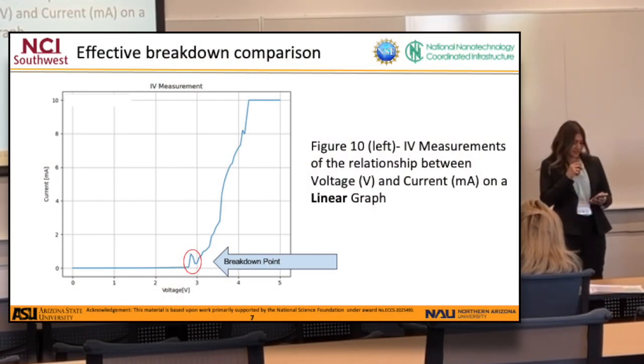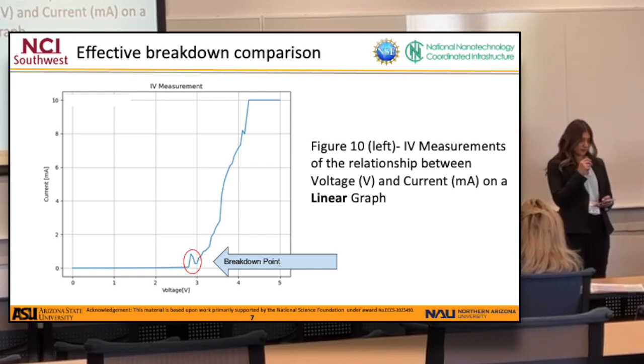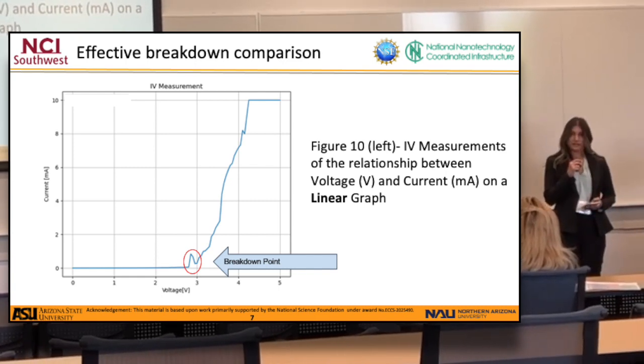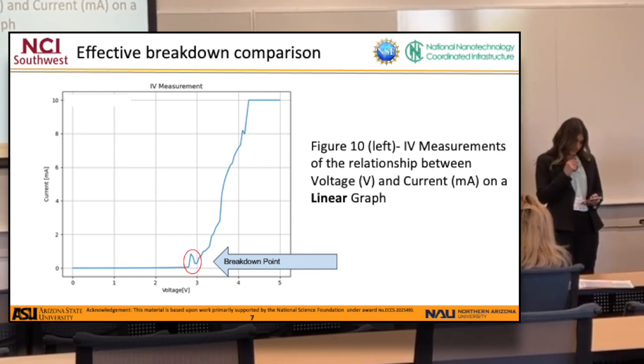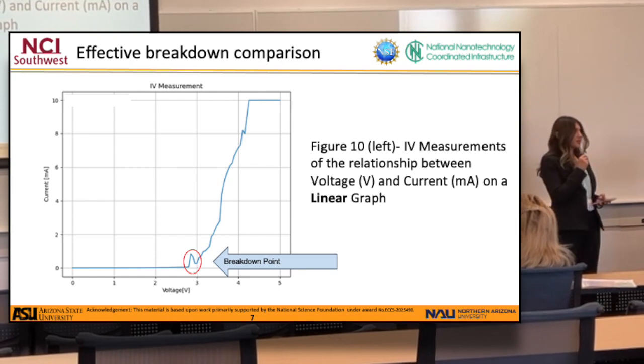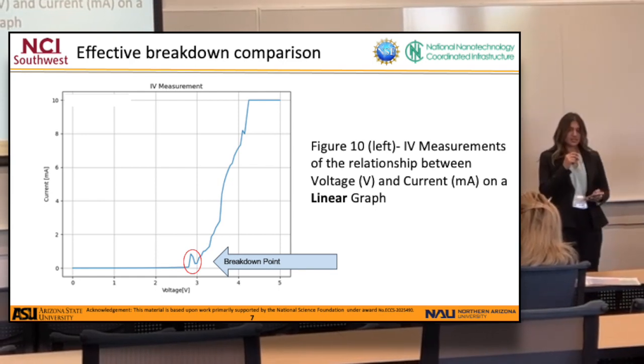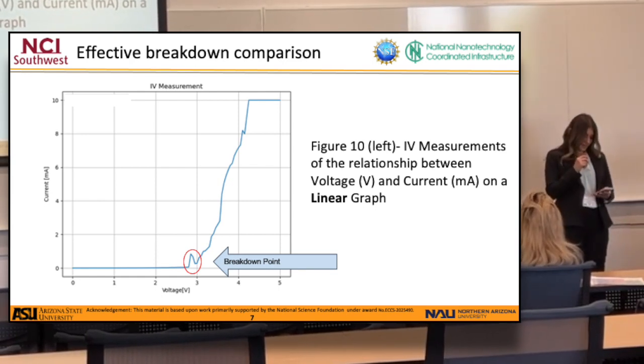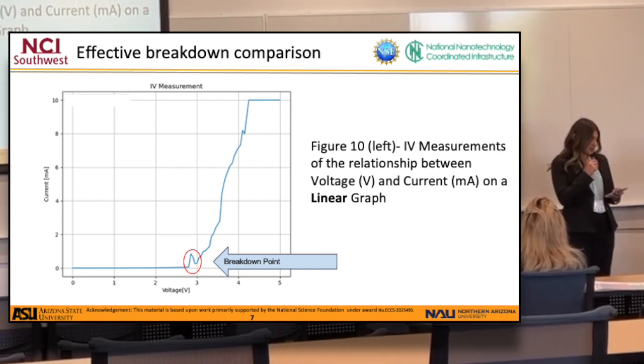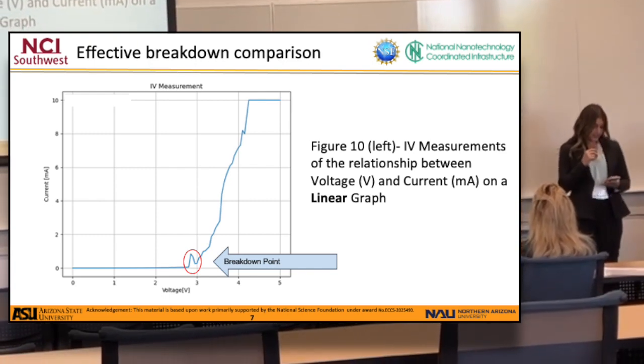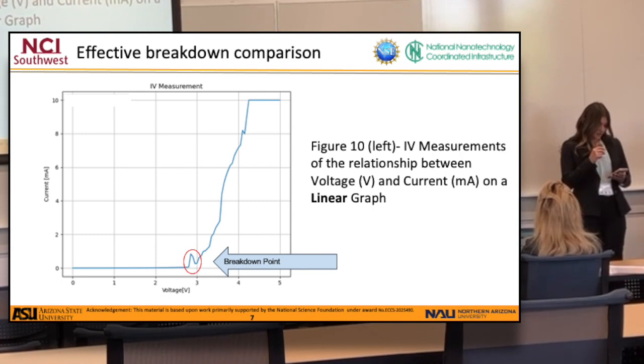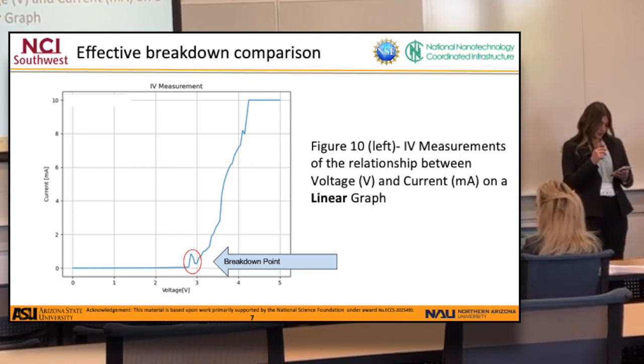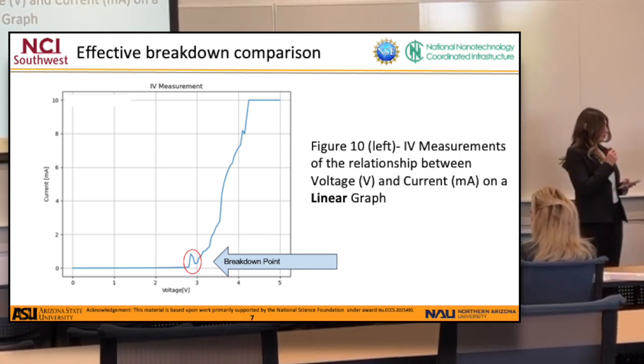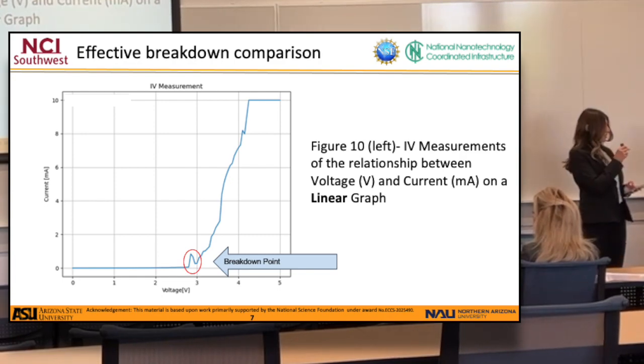The linear IV curve demonstrates the relationship between voltage applied and the current that flows through the device. It is significant to take note of this because we can determine conductivity, resistance, and breakdown point. An effective measurement properly showing where breakdown occurs is indicated by the current rising until there's a distinct upturn, which in this graph is shown just before 3 volts, highlighted by that red circle.